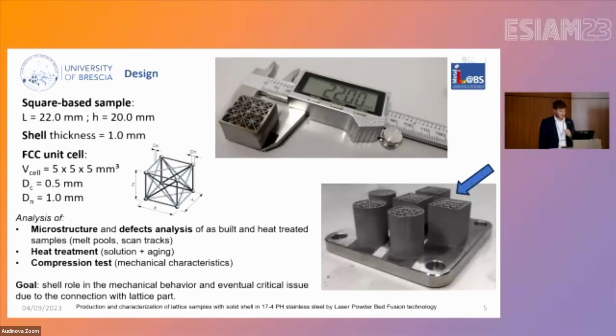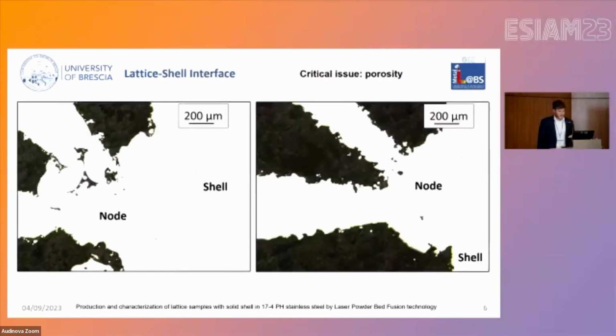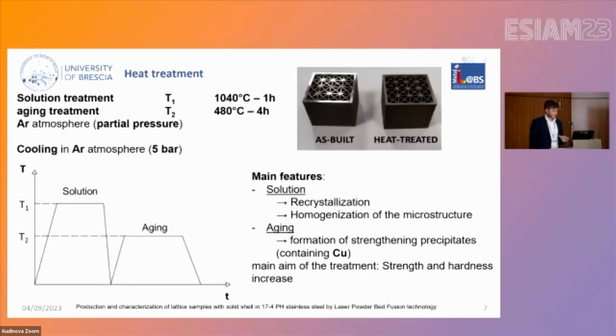The goal, as I said before, was to understand the role of the shell on the mechanical behavior and any critical issue at the interface due to the connection of the lattice part to the solid part. Let's start to understand what happens with this interaction. We said at the beginning, after the production of the sample, to see what the critical issues are. In particular, it can be noted here the presence of porosity and also here, but it is also important to see that we don't have a perfect spherical node here, but we have a sort of distortion of the geometry. But this is normal because we pass from a small size of the strut to the higher dimension of the solid shell. After this first analysis, we also performed the heat treatment.